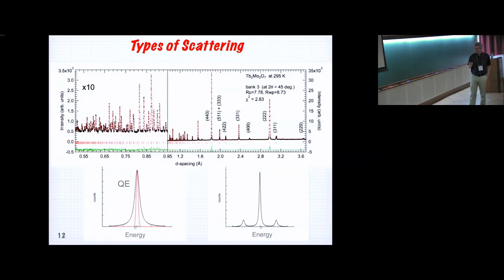So from scattering or from neutrons or X-rays, we can do the diffraction. So here we don't care about energy, and we look at crystal structures or spin structures. We can work out the arrangement of ferromagnets and antiferromagnets from where the Bragg peaks appear. And there's lots of software now that easily does that. You run through to minimize the fitting, and you're looking for the intensities and the positions to get all the information. And you see with neutrons here on a pyrochlore, over a wide range, you can get a lot of information on the crystal structure. And from this, we were able to say this pyrochlore, which is a glassy pyrochlore, has a well-defined crystal structure. Now, I say that here, and I correct myself later. This is a bulk measurement.